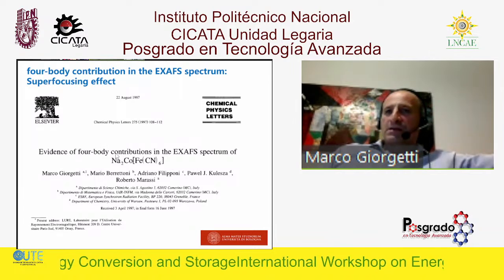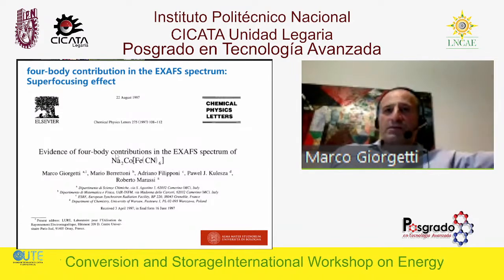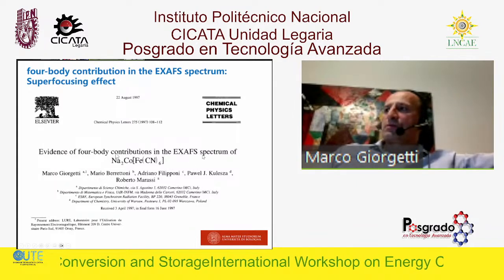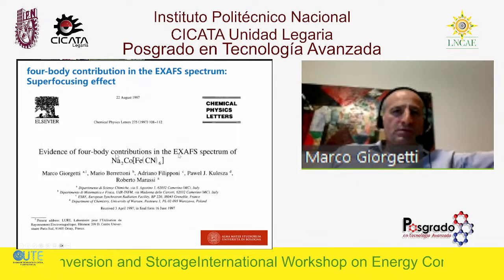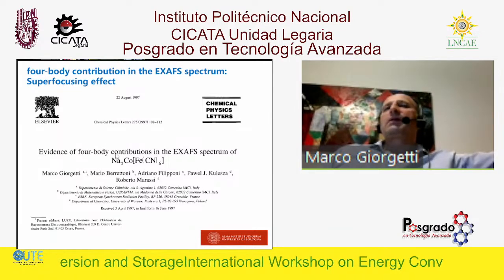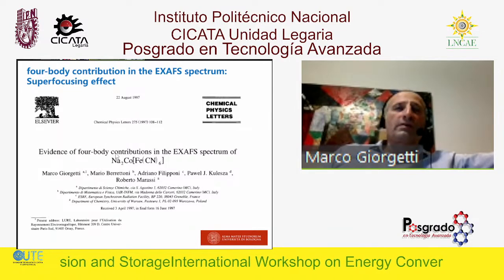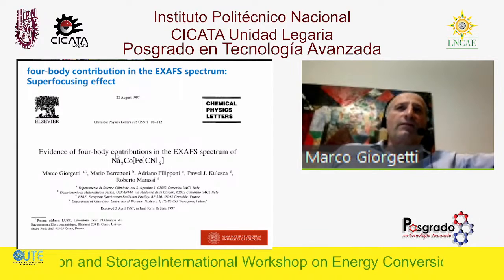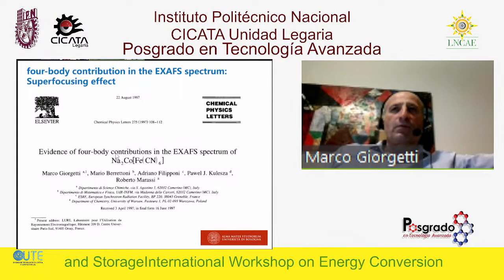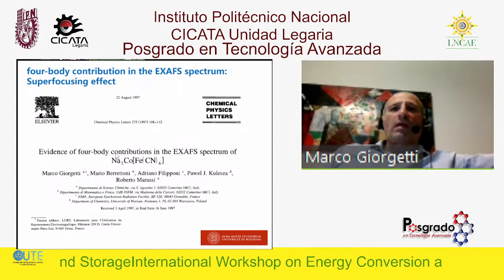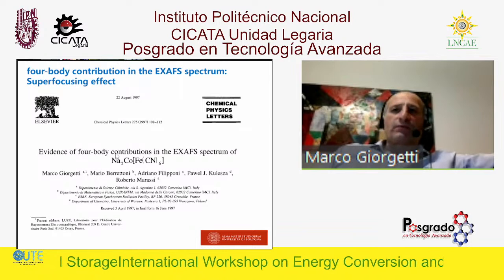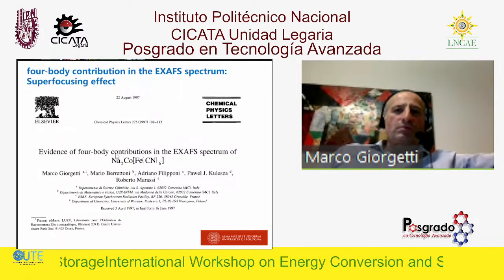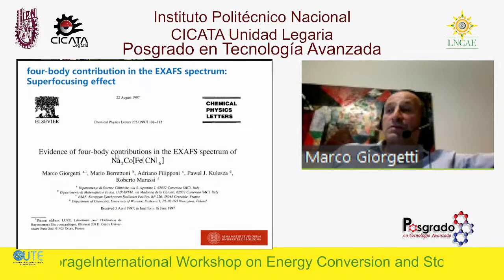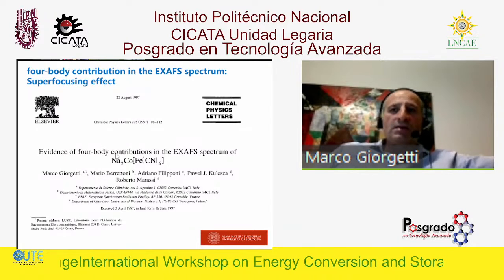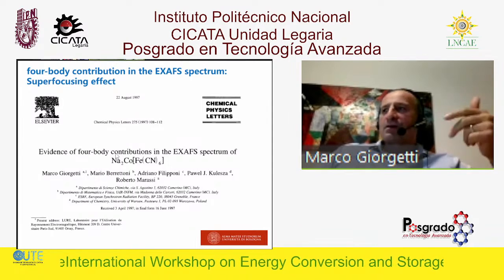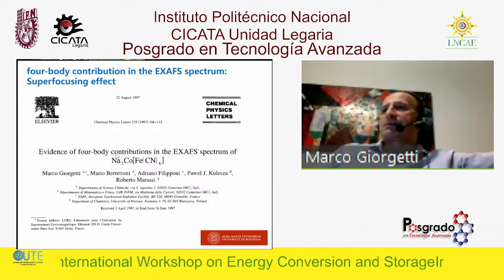And in fact, it has been seen in the past, in this first paper, that the EXAFS signal associated to this material is enormous. When you have a very large signal, it's a good point, because it's difficult to treat from the theoretical viewpoint, but then you have a wealth of information that you can extract from the signal. And that was due to the peculiar structure of the metal cyanoferrates, which are characterized as perfect linear chains, high degeneracy of the chains, and also a close distance between the two metal sites.